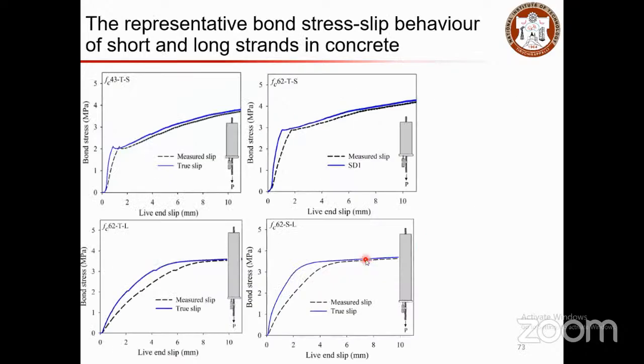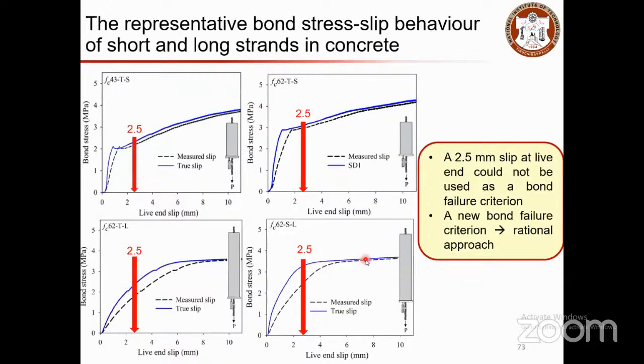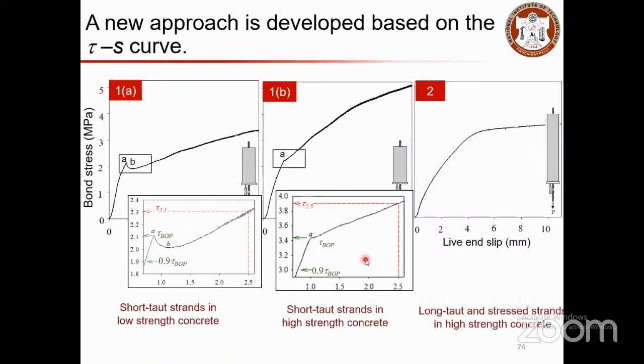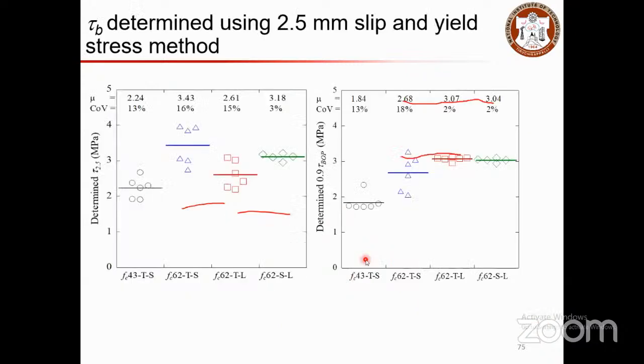From the testing, we understood the behavior of the strands in concrete, and from that behavior, failure criteria and test methods were also proposed. We understood that when the tensile stress increases, bond stress increases, and when the embedded length increases, bond stress also increases. This is for the short span, and this is for the long span.